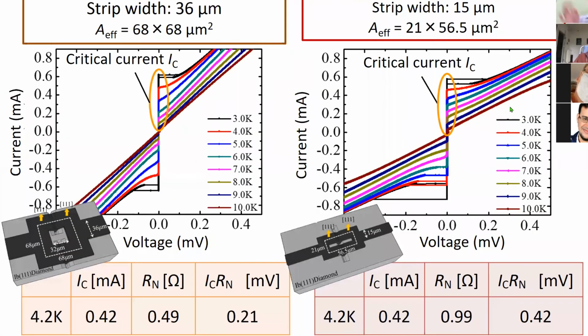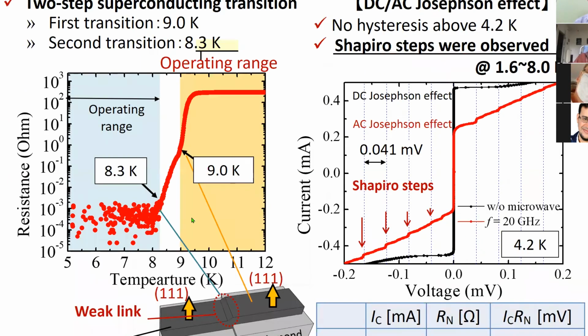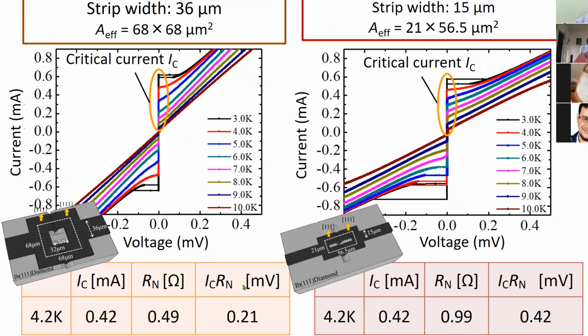So in two cases, we just measured the IV characteristic as a function of temperature, and then we of course measure the ICRN, which is one of the parameters to evaluate how much Josephson junction we get.